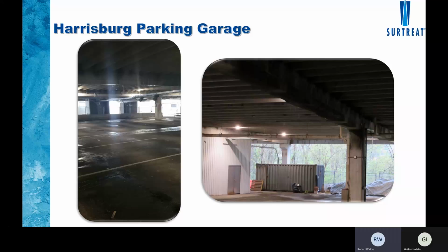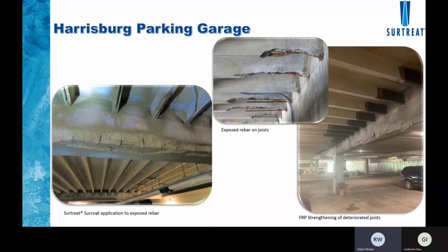We had problems with concrete, and we have a little video here that we can show where we're going through the garage, treating it. We can see we have damage to the ceilings and whatnot. But here we have another picture of this garage. And what happened here, we had damage to the beam ends. And you can see here damage to the center parts of the beam. Concrete was lost. Well, the engineer for Harrisburg Parking Authority was alarmed by this problem. And he said, look, you've got to reinforce and fix these beam ends because the major cause of damage to parking structures is shear failure from the deck.